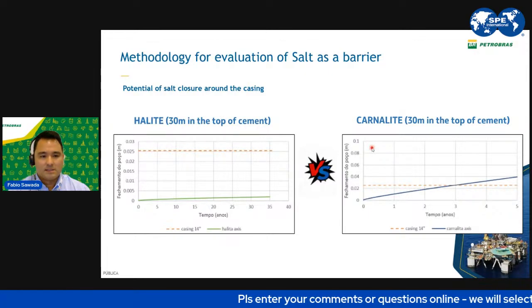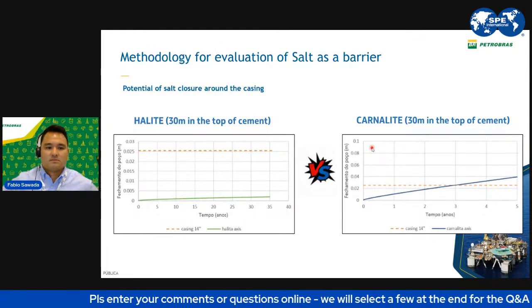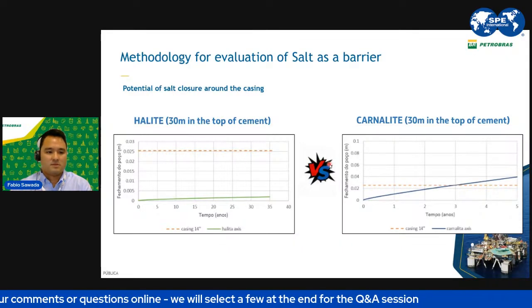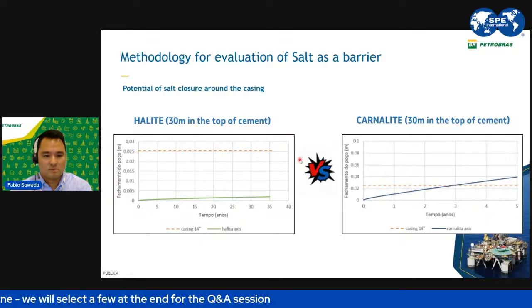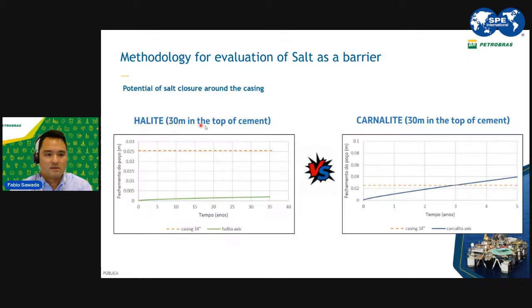Now I'm gonna show you an example of application of that double creep model. Here we can see an example of a simulation that was applied to a real well, but we assumed that at the top of cement, in the salt section, we have a 30-meter halite, and in the second case, we have 30 meters of carnallite. The carnallite is known to have a higher creep rate compared to halite, and the tachyhydrite has an even higher one than carnallite. So, depending on the lithology, the velocity that the salt would creep changes very much.